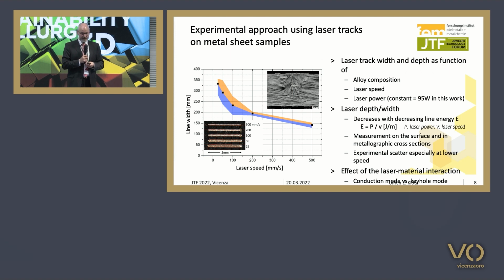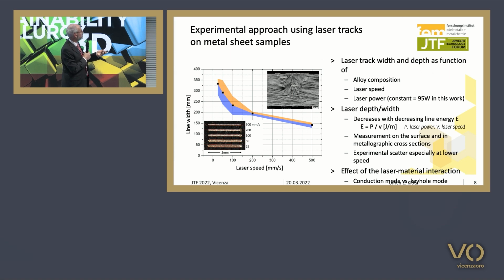Here's an example of how the line width of this laser track depends on the laser speed. We see, as shown in the picture, that with increasing laser speed, the laser width decreases and the process gets more stable, because the scattering is reduced—shown here by the color range representing maximum and minimum values. Here we see a cross section: the sheet material, the deformed sheet material, and the cross section of the laser track.